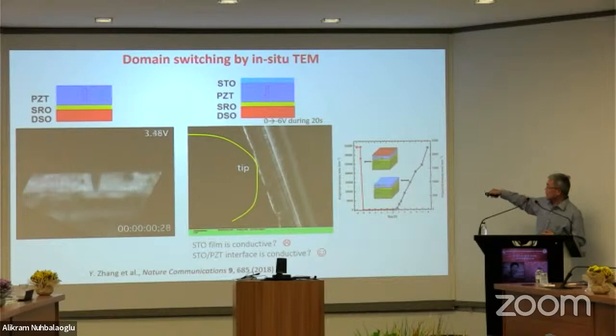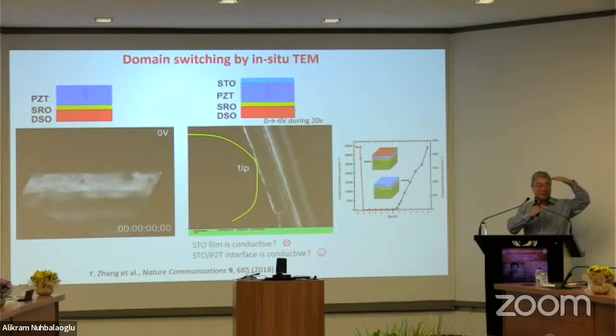This means that there's a bottom electrode, and there must be a top electrode, but we did not intentionally make a top electrode because STO is supposed to be insulating. This indicates that either the STO is conductive or the STO-ferroelectric interface is conductive. To rule out that STO itself is conductive, we tried different STO layers with different thicknesses. If the conductivity is switchable and scalable, then STO is conductive. We did that with many different STO thicknesses and always got the same conductivity, so it is not scalable. We conclude the interface is conductive.